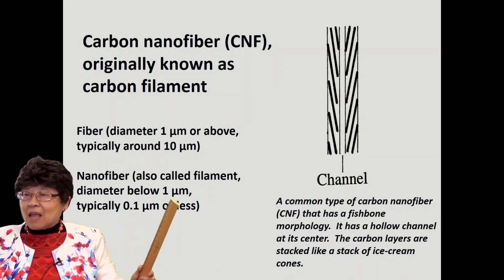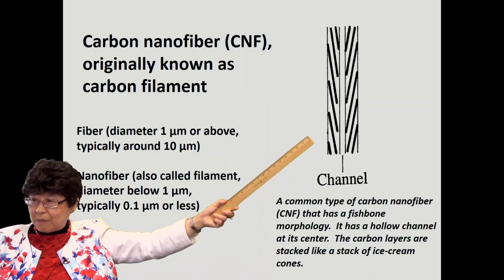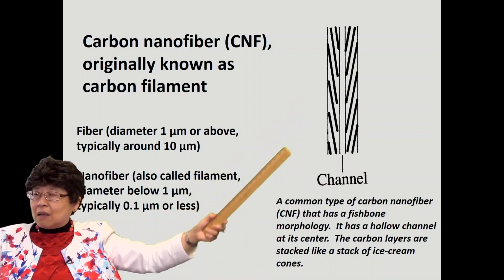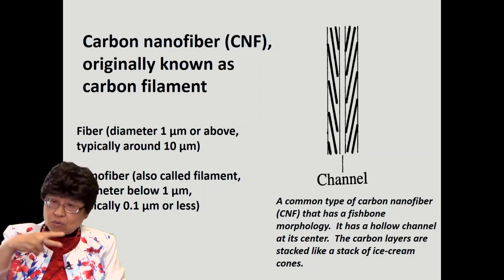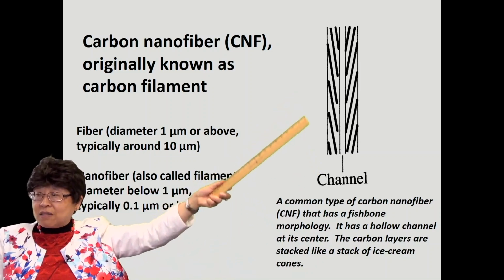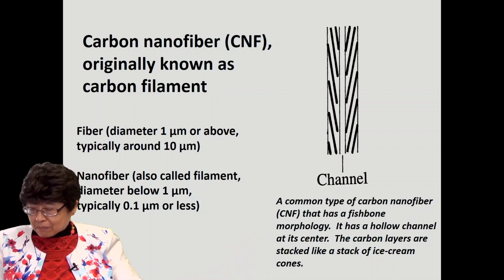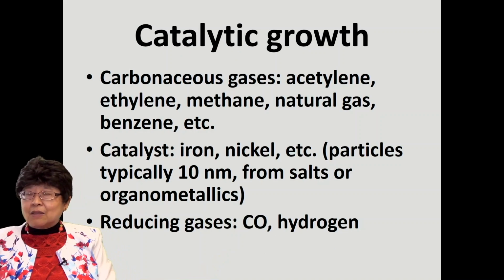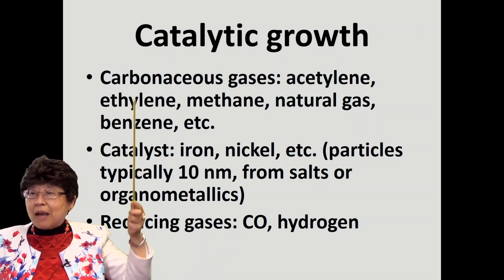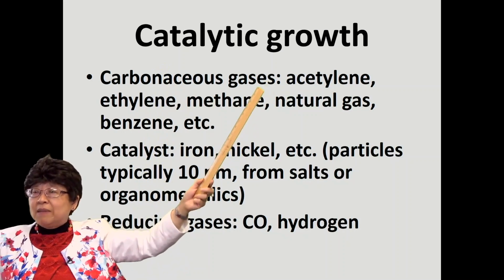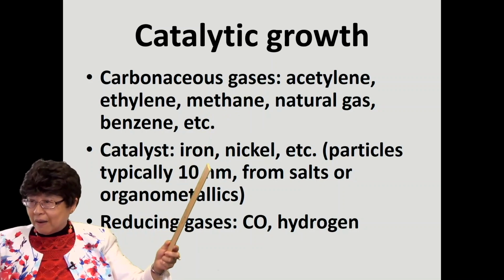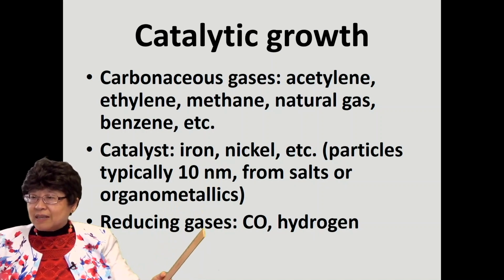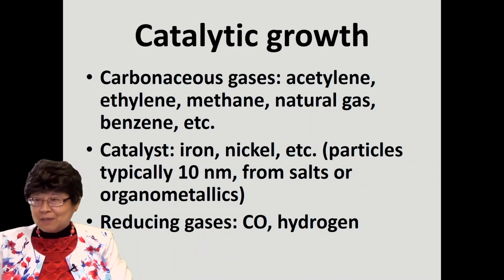And this is a common type of carbon nanofiber, which has a structure like a stack of ice cream cones with the tip of each cone cut off. And the cross-sectional view makes it look like a fishbone, and therefore this is called fishbone morphology. The carbon nanofiber is typically made by catalytic growth using a carbonaceous gas such as acetylene as the carbon source. And the catalyst is typically iron or nickel. And you need a reducing gas so that it wouldn't oxidize once the carbon is formed.